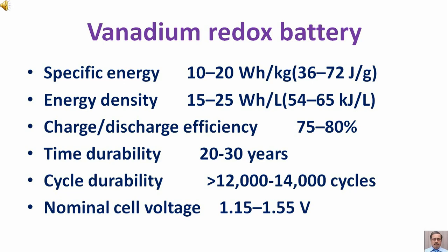Charge-discharge efficiency is between 75 to 80%. Time durability is 20 to 30 years. Cycle durability is greater than 12,000 to 14,000 cycles. Nominal cell voltage is from 1.15 to 1.55 volt.